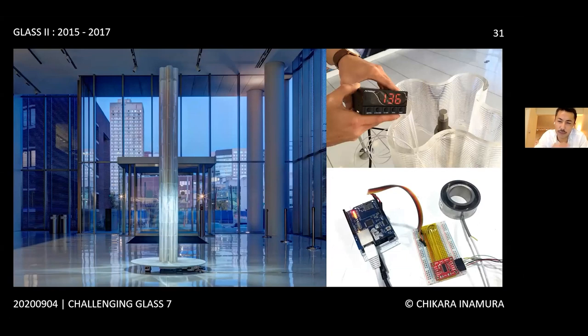We built a mock-up at the lobby of the Media Lab and examined the construction process and the structural behavior of this glass column. The column is made of 15 unique components that are vertically assembled. Self-leveling transparent silicone adhesive was applied on one side of each component to provide a dampening layer and prevent stress concentration at the interface. The assembly is then post-tensioned with two steel plates at the top and bottom of the column that are connected with a steel shaft inside the column.